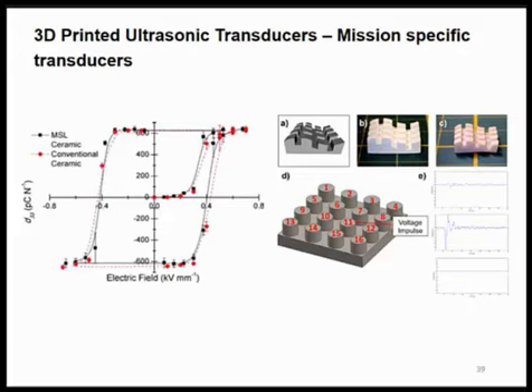So we can make piezo arrays, we can make curved piezo arrays, we can change the shape of the pillars in piezo arrays as well, and change the cross-coupling behaviour. Can't really see the graph at the end there, but it's basically showing there's very little cross-coupling between those. So it's as good as conventional process, but we've got much more control over the structure.